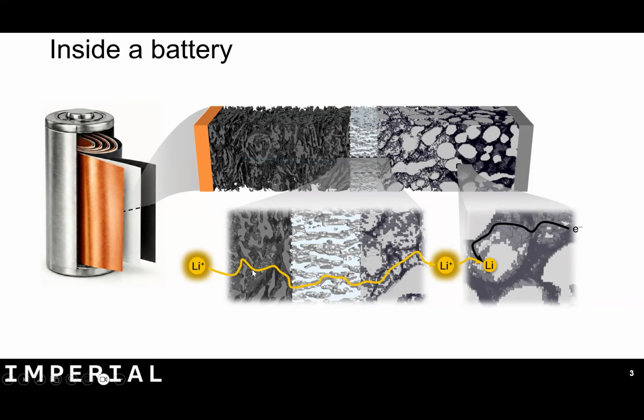And the point is that in order to liberate energy from the system, the lithium ions need to escape from a particle of graphite, travel through the pore network of the anode and the separator and the cathode, and enter a particle of the cathode active material. And the wiggliness of those pores will, in effect, slow down the transport of the ion and therefore create an overpotential and reduce the amount of energy you can extract from your system at a particular power.